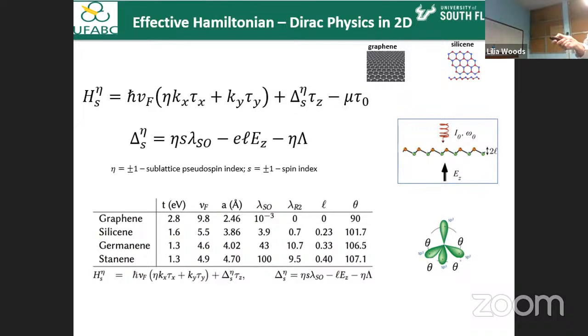Okay, and as you see, this energy gap now has two indices. One is a sublattice index, one is the spin index. And you have several parameters. We have the spin-orbit coupling, which for graphene is almost non-existent, but for the other materials it can grow substantially. There is the staggering parameter that allows us to open a gap, and of course there is the laser parameter that is a composite parameter of the intensity and the frequency of the laser.